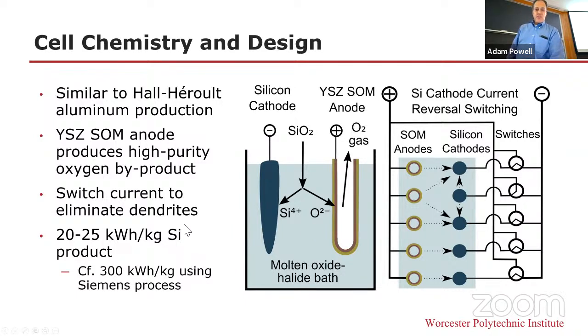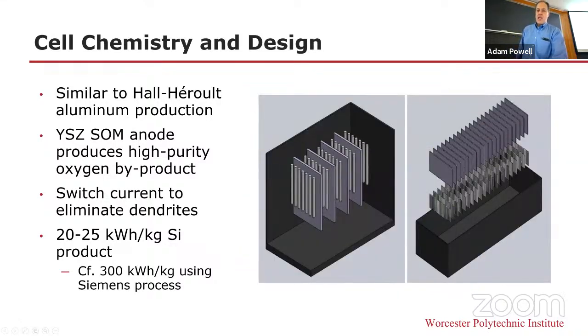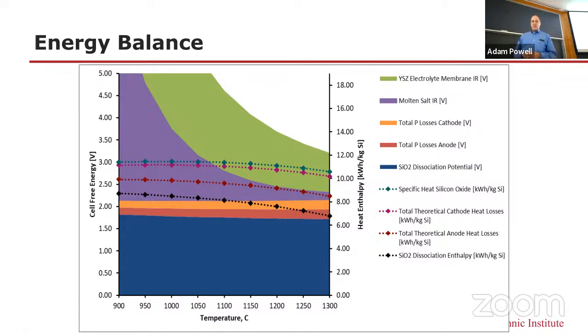The big payoff is the energy reduction, 90% versus the Siemens process, let alone the much greater simplicity. A single step or maybe 2 steps from raw silica out of the ground to a silicon product you can use. This is what it would look like scaled up, making silicon slabs with the zirconia tubes, and a larger high current cell would look something like this. This is the energy balance, the thermal energy in versus the voltage stack, the energy. 2 different kinds of energy: the free energy and the thermal energy used to reduce the silica.